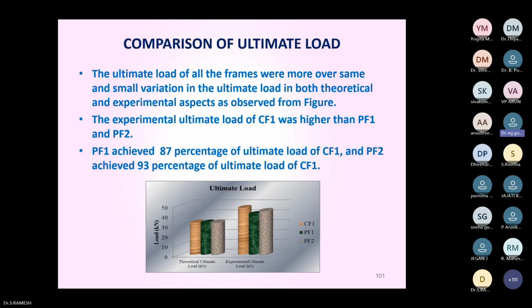Comparison of ultimate load. The ultimate loads of all the frames were more or less the same, with small variation between theoretical and experimental values, as observed from the figure. The experimental ultimate load of CF1 was higher than PF1 and PF2. PF1 achieved 87% of the ultimate load of CF1, and PF2 achieved 93% of the ultimate load of CF1. So PF2, prefabricated joint 2, the beam to column joint wrapping method, is the best one. From the research, we got this result. Next.